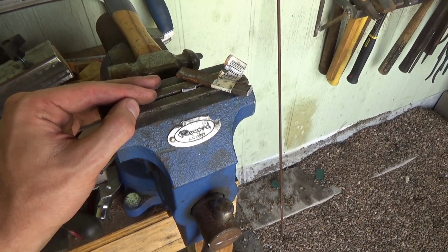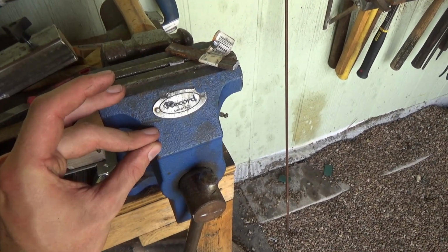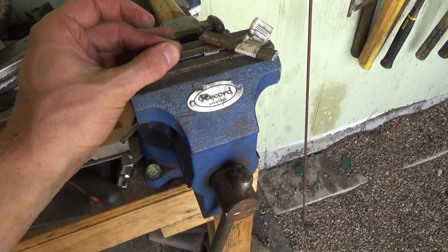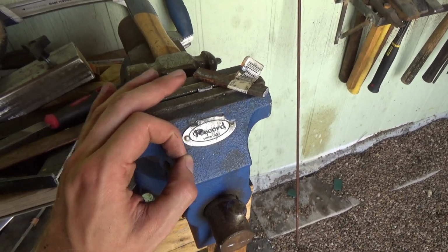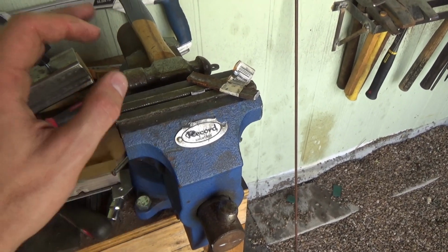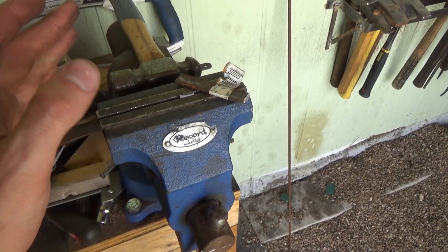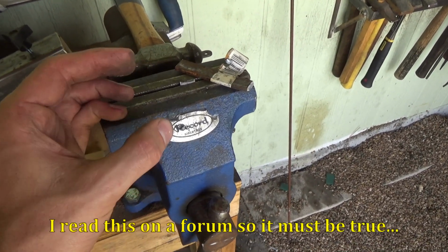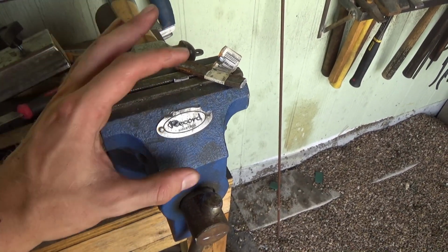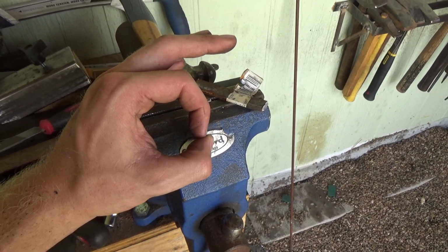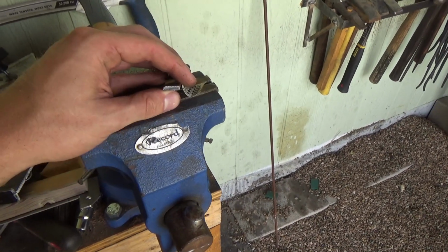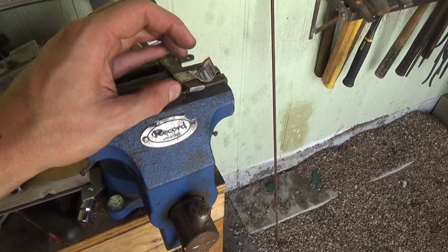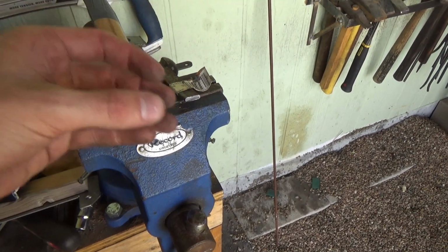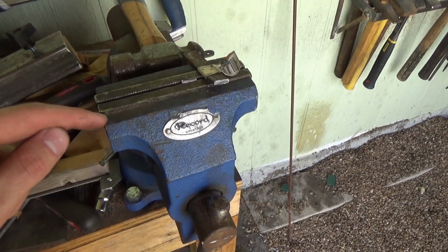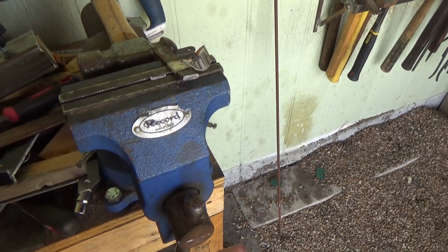If you have excess carbon, that carbon is now again outside of the crystal structure, and no matter how hard you get the iron crystals, you have soft graphite inclusions from the additional carbon. This can be remedied in certain ways, such as the inclusion of a nodularizing element, which causes those graphite flakes to form into spherical graphite nodules, which distribute stress evenly. Otherwise, you get graphite inclusions that are flakes, and they can break very easily, they shear very easily, much like pencil lead or pure mineral graphite, and a crack can propagate from right here all the way through over here in the blink of an eye. You just start to get a crack and then add any more stress and it breaks.